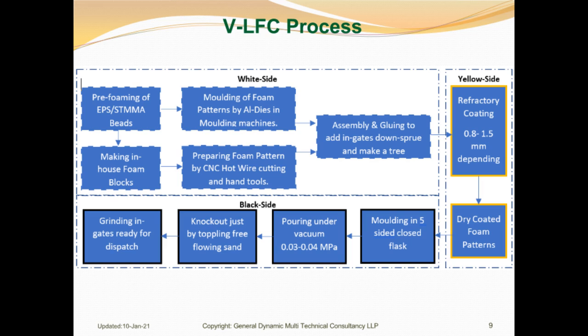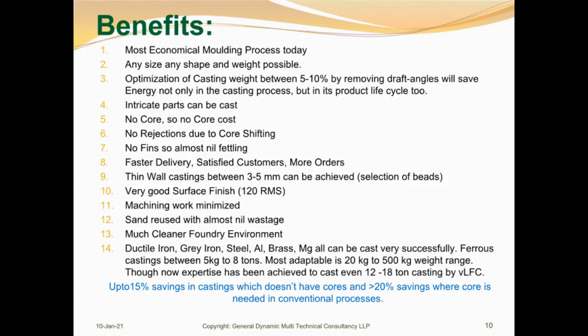These foam patterns are assembled and made into clusters or a tree in case of small castings, and then ingate, runner, risers etc. are prepared and glued. This tree is then coated with a refractory layer and dried for 4 to 6 hours. These dried foam pattern assemblies are put in a vacuum flask and sand is compacted around it with a 3D vibrator. The vacuum is applied while pouring for a few minutes. Then after cooling, the casting is brought to the knockout area, where the casting is extracted and the free-flowing sand goes for cleaning and cooling.